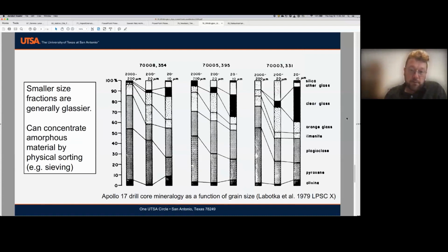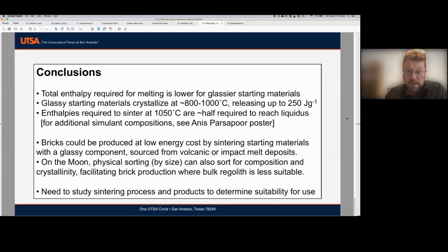So this interesting thing is, as we know, the smaller size fractions in the lunar regolith are generally glassier, which means that we can concentrate amorphous material simply by physical sorting, so sieving or something else. But if we can get lots and lots of the fine material, it's going to be glassier. Next slide, please. And that means it's going to take less energy to do things with it, whether that be sintering or complete melting. So if you're interested in this, I also encourage you to see the poster by my postdoc, Anis Parsapur, which is on other simulant materials.